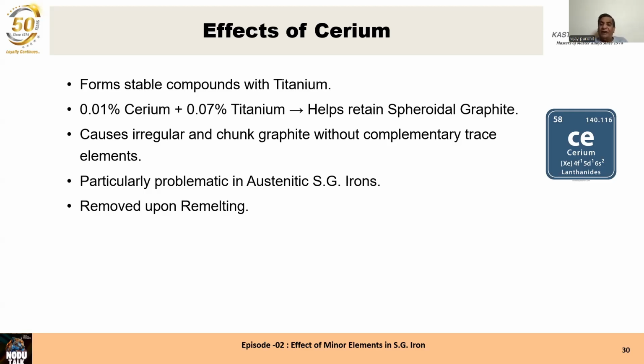If bad elements are present and cerium is not used, then we get these degenerated forms of graphite in the microstructure. So you have to be careful and knowledgeable enough to find out if bad elements are present and use cerium, and if bad elements are absent, do not use cerium. We can't remove these elements from the metal. We can only dilute them to some extent by using high quality pig iron like Sorel pig iron. If the bad elements are present to a large extent, cerium will help. But if the bad elements are absent, the cerium will promote chunky graphite. So you have to be very careful and vigilant when your raw materials enter the foundry.